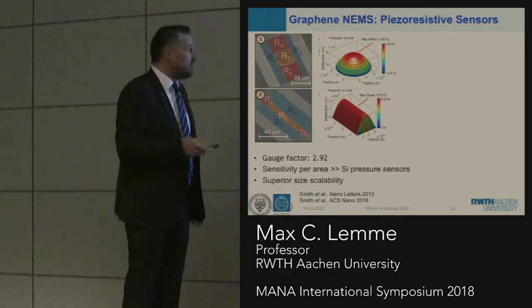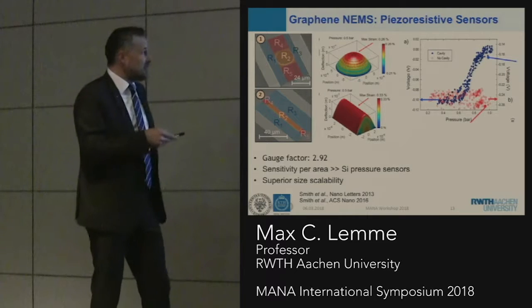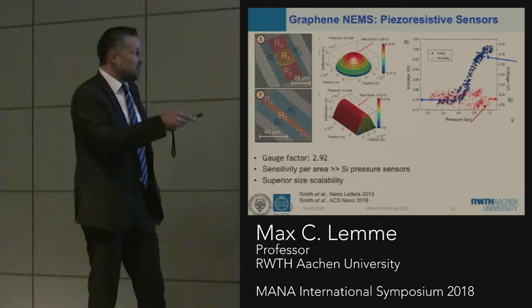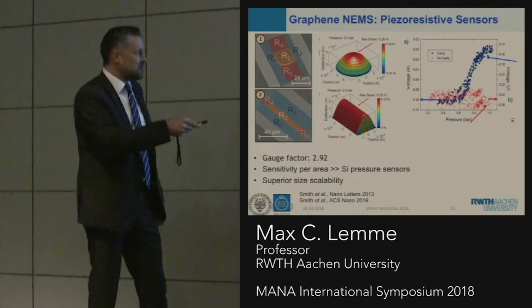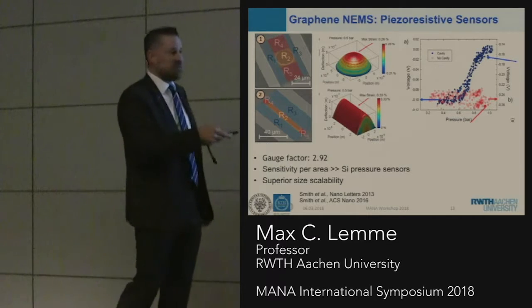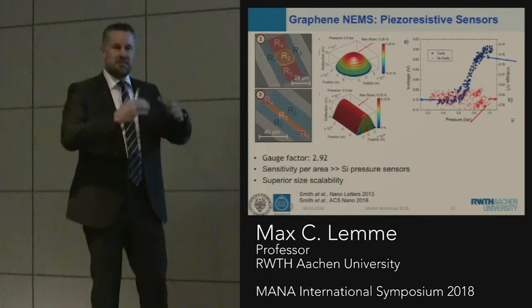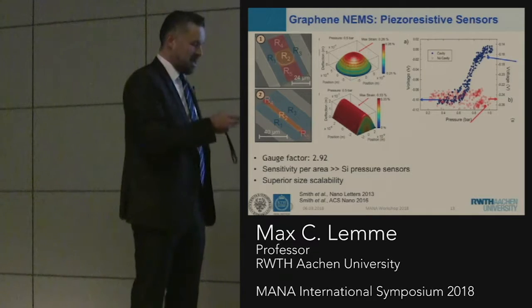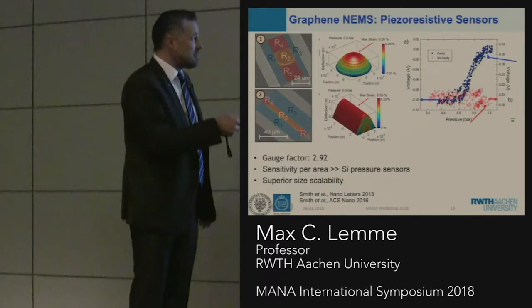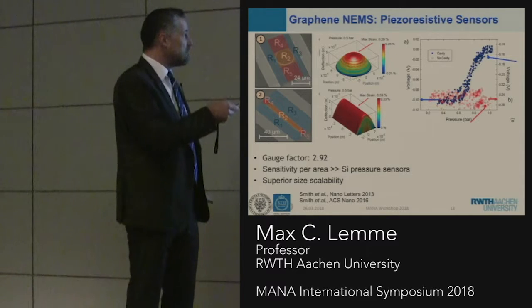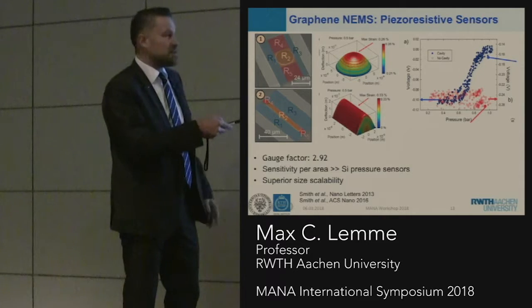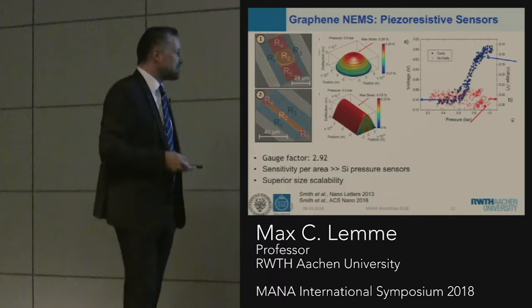At the end of the day we were able to measure with these membranes - this is the pressure, this is the voltage across the membrane - and you see the piezoresistive effect here. The resistance changes as a function of pressure, which means the deflection of the membrane and the strain in the membrane. The red curve is actually a reference patch of graphene without a membrane, so you see there's no signal here.